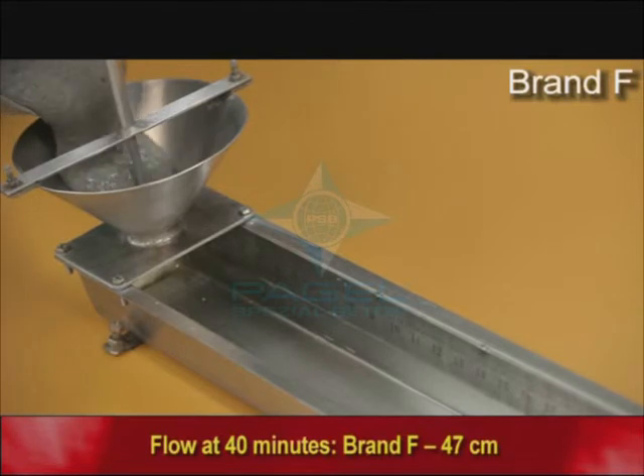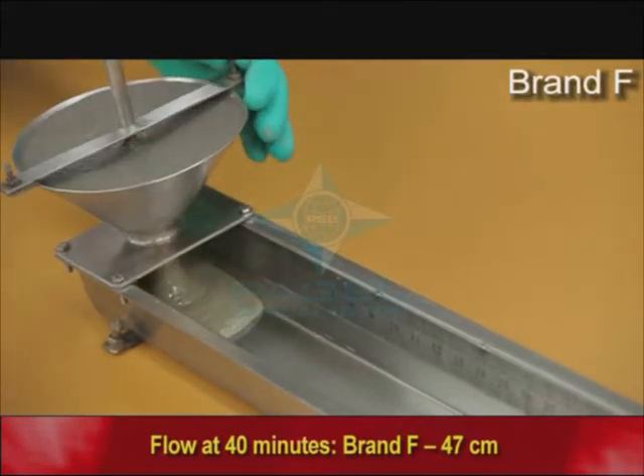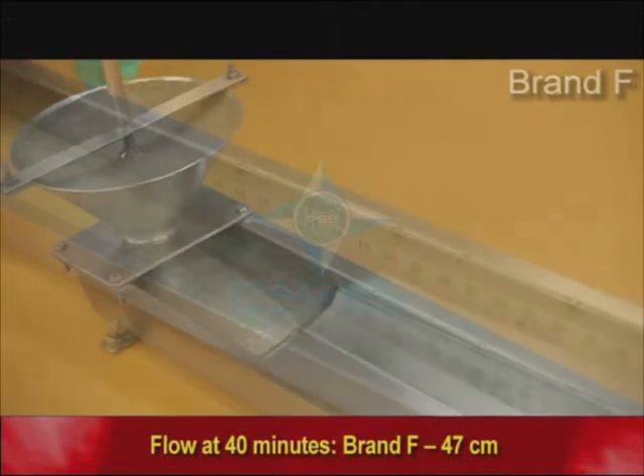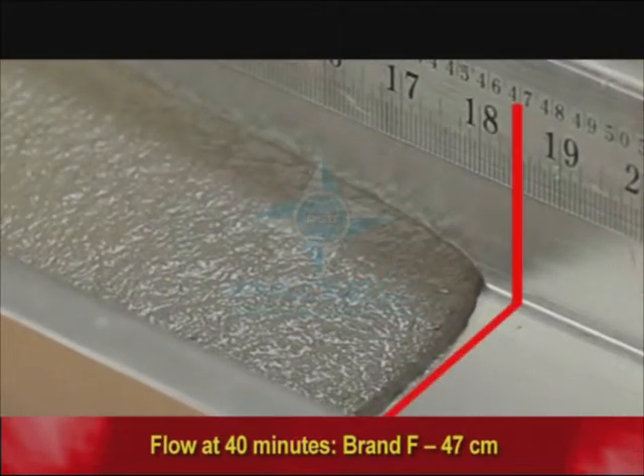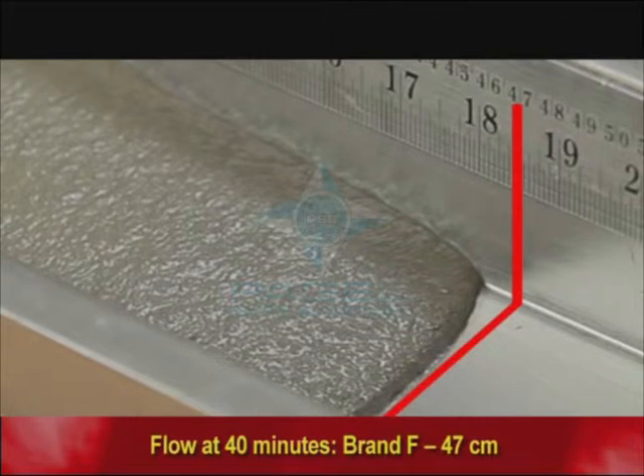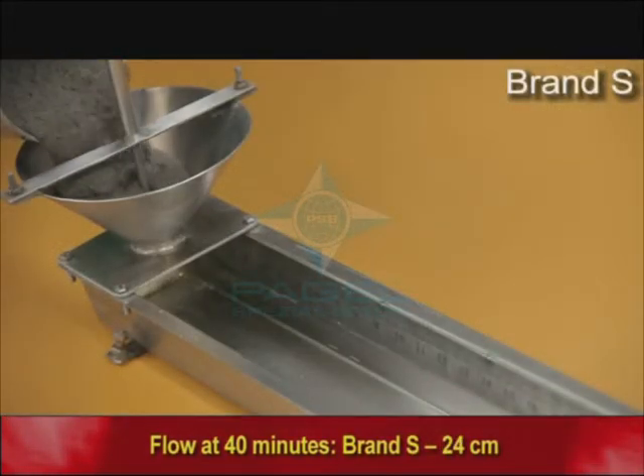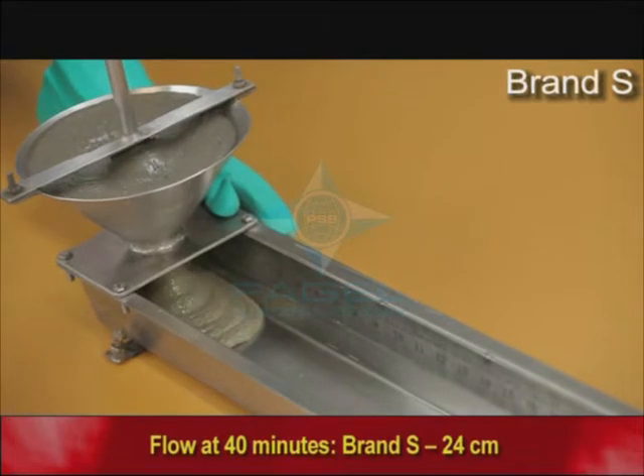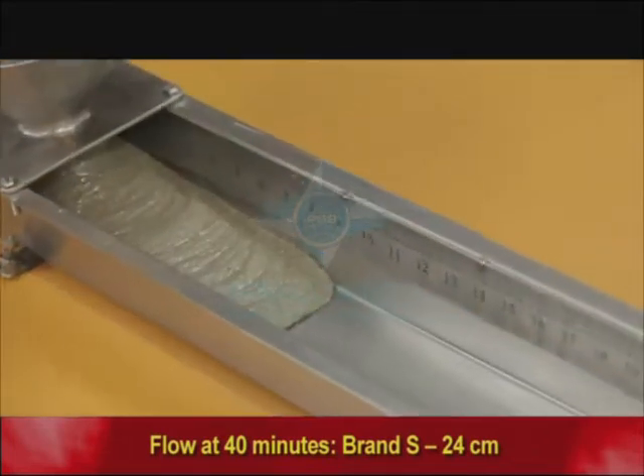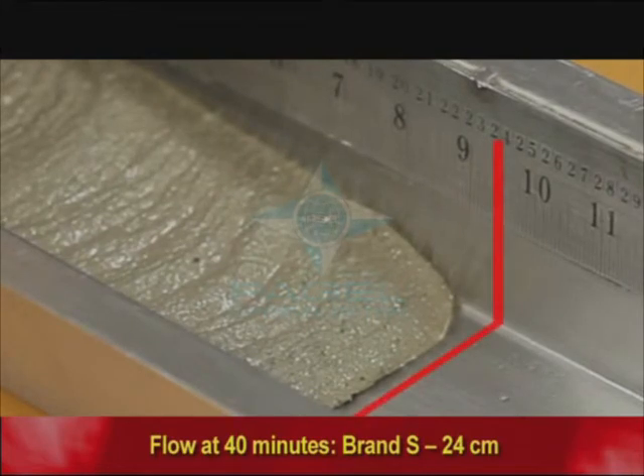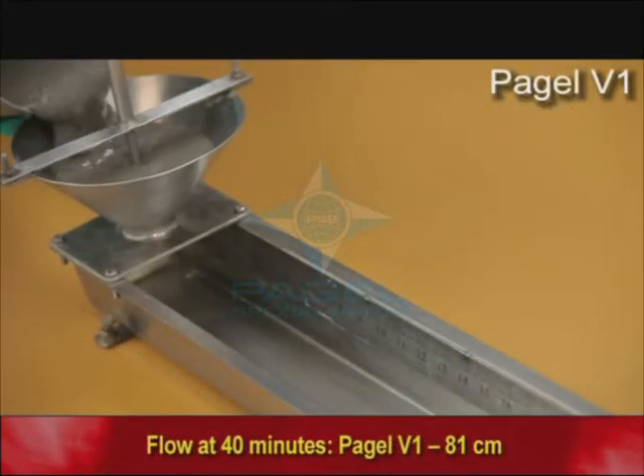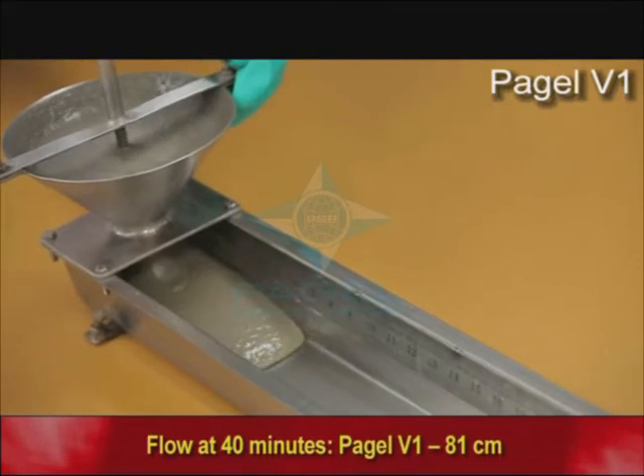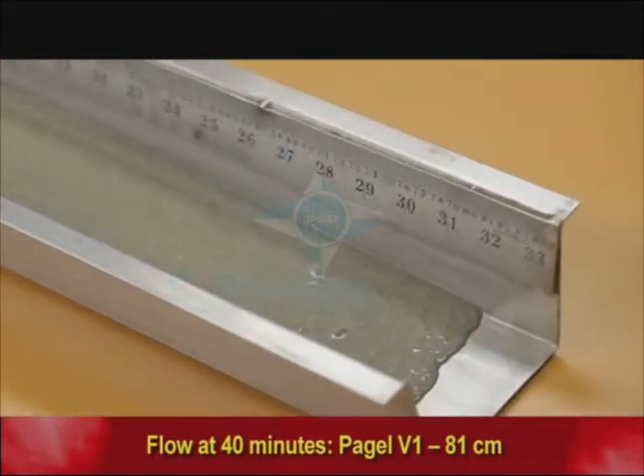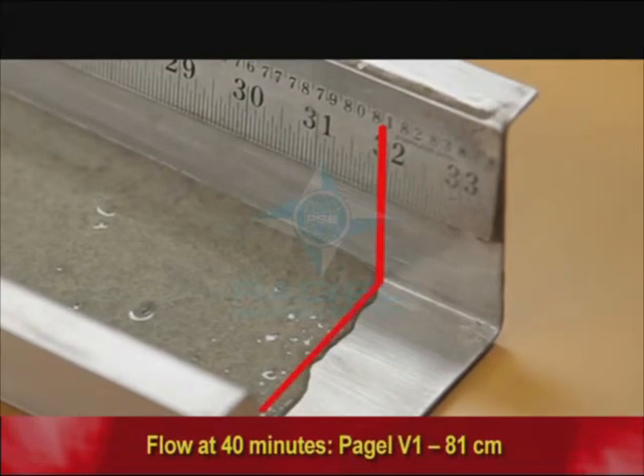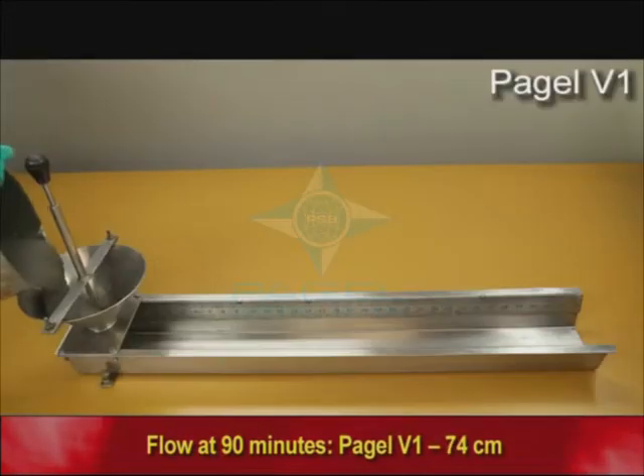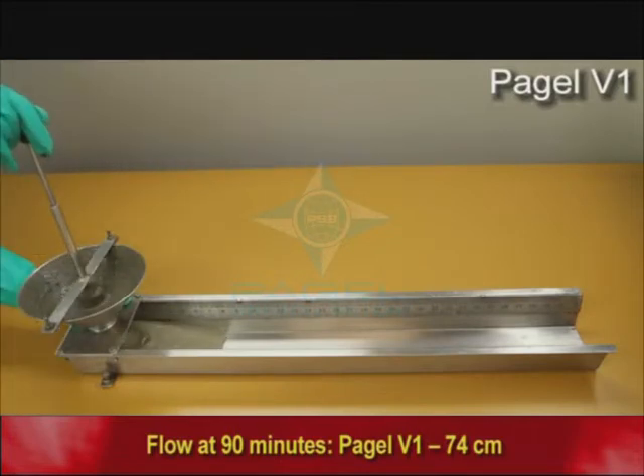As you can see in this flow test, after just 40 minutes, the grout of brand F flows very slowly and only reaches 47 centimeters. Brand S flows like heavy sludge and achieves a minuscule 24 centimeters. However, the Pagel V1 grout flows as easily as it did at 0 minutes and reaches a vastly superior 81 centimeters.